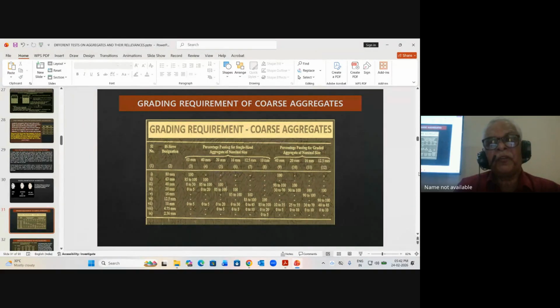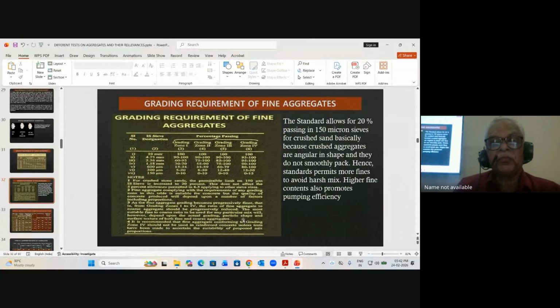So, grading requirement of aggregates - IS standards have given some limits for single size aggregates. What is more important is, of course, for coarse and fine aggregate also it has given something. What is more interesting here is Indian standards allow for 20% passing in 150 micron sieves, but for normal river sand it allows only 10%.